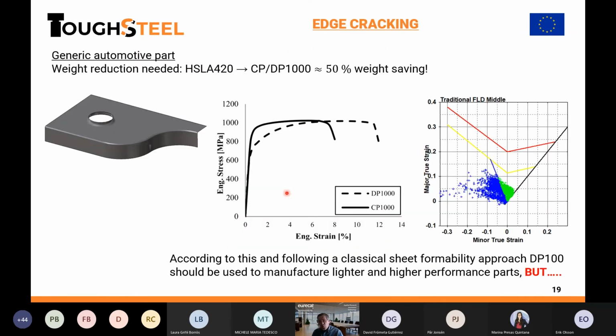So let's explore this concept of edge cracking. Let's just make an exercise, to see how we can understand this. This is a fake part, just to show what we want to do. If we use a normal low strength material, this is a low alloy steel with a yield strength of above 400. If we want to reduce the weight, we have high strength steels. For instance, we can choose a material of 1000 megapascals strength, a CP or a DP, complex phase or dual phase. We get a 50% weight saving. That's super. We go for that.